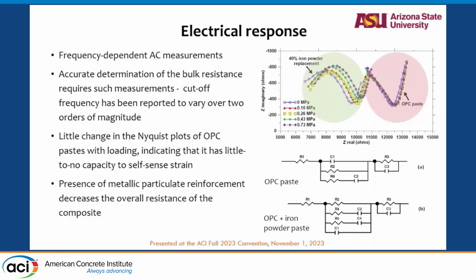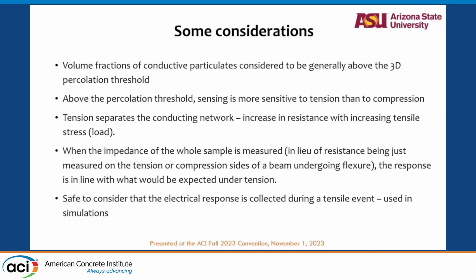This is a general AC frequency-dependent measurement of the resistance that we do. The consideration here is that we are assuming the percolation threshold is reached, because these are in the range of 10, 20, 30, 40% replacement. We are not trying to figure out what changes the percolation threshold.